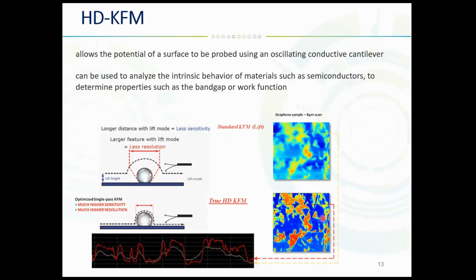And here's the direct comparison between two techniques. Here we're taking the scan of the graphene sample, and the contact potential images that we obtain in a single pass setup provide better contrast and lateral resolution of the graphene domains. This is due to the fact that in a single pass approach, the tip is oscillating closer to the surface, typically 0.1, 0.3 nanometers, or even touching the surface intermittently, in comparison with the double pass mode or lift mode, which is typically above the surface about 10 to 20 nanometers. So this is how we can increase the resolution as well.